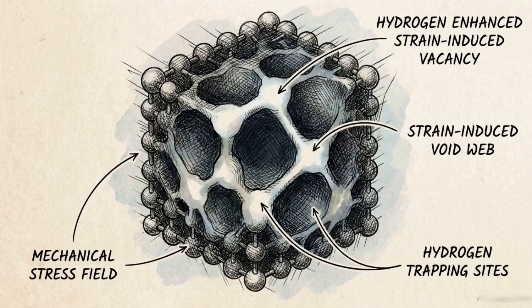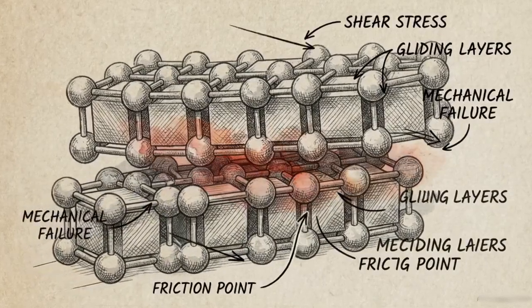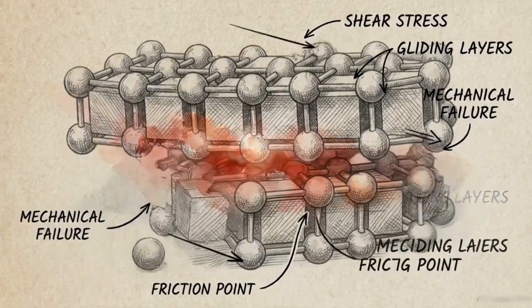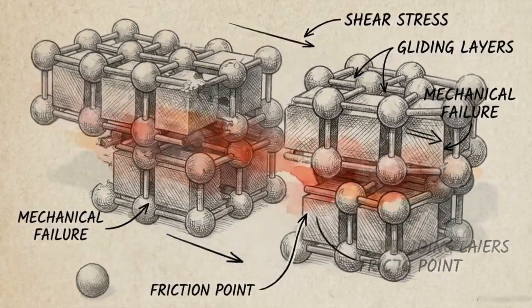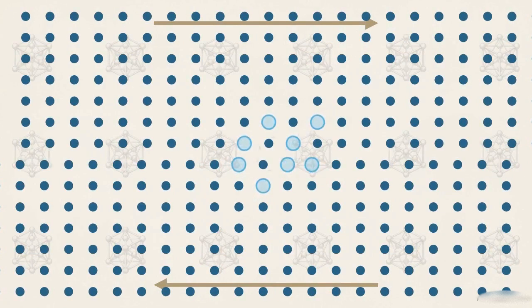Once the hydrogen accumulates, we see the primary degradation model take over: hydrogen-enhanced strain-induced vacancy, or HESIV. Trapped hydrogen has a counterintuitive effect. It locally enhances plasticity. Under stress, atomic layers that should remain locked begin shearing and gliding past one another. This localized plasticity forces the rapid generation of atomic vacancies, literal empty spaces in the lattice where metal atoms are now missing. Under the continuous mechanical stress of a firing engine, these microscopic vacancies slide together and coalesce into pronounced microvoids. These accumulating voids destroy the cohesive strength of the metal from the inside out.